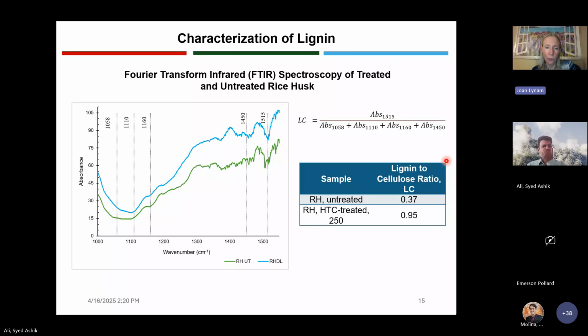The untreated one is the green one. The treated one is the blue curve. We calculated those things and found that in rice husks, if you don't treat them, the lignin to cellulose ratio is about 0.4. But if you do treat it, you get about a 0.95 lignin to cellulose ratio. So it proved basically that we took out the cellulose from these rice husks. So we can go on to the next one.